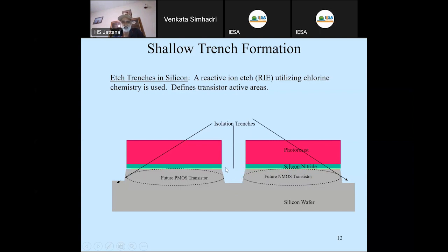It's vertical because it's a trench, and the width and the depth of this are almost of the same dimension. So aspect ratio is close to 1.2 kind of thing. And so we will make a trench, and then finally we will fill this trench with oxide, very dense oxide, because it's an isolation. You can see here we will fabricate a P transistor here, we will fabricate an N transistor here. So it's an isolation and it's a cross section. From the top, if you see, it will be a boundary wall across the house. It is like that.